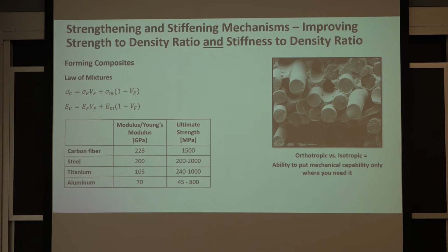But if you don't use the strength in the transverse direction, then that's wasted weight. You're not getting anything from it. A composite is very different in that you can tailor the properties so that you're only putting the mechanical capability, and therefore the extra weight, the extra density, only where you need it. And that's one of the reasons that carbon fiber, fiberglass can be very effective at making strong, lightweight structures.